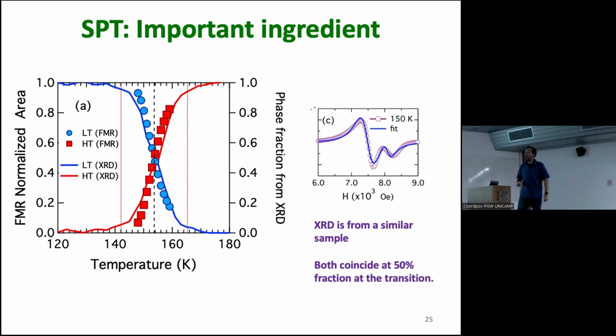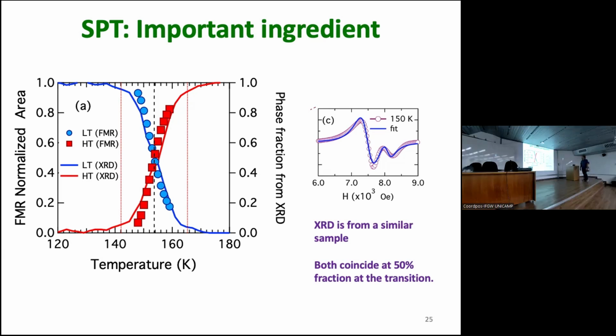And then if I plot both of them in the same graph, I get something like this. They match perfectly. So what this is telling me is that whatever is driving this is related exactly to the crystallographic structure of the vanadium oxide. Okay?